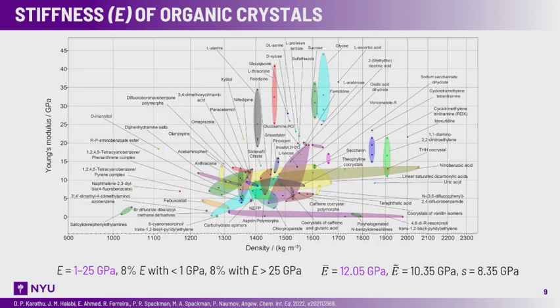And if you further zoom into this region, you will see that indeed there are outstanding crystals which can compete with some much harder materials. And we found that there are two classes of very hard organic crystals, perhaps most prospective for applications. These are either crystals having a lot of hydrogen bonds surrounding a central core, or crystals having charge-assisted hydrogen bonds between zwitterionic molecules. And so perhaps those are the first candidates that we can consider when we think about applications.